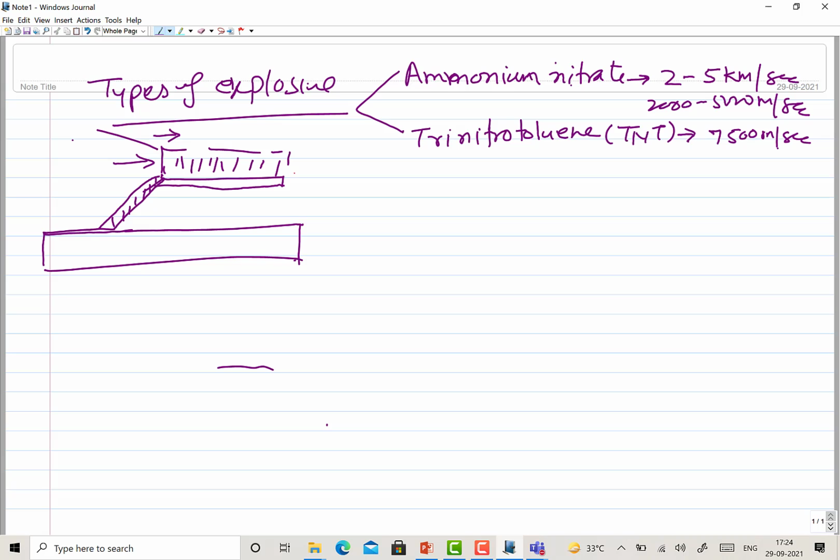So it will give you low collision angles. Something which bends fast, soft and ductile, of low yield strength, under the impulse pressure of the explosive will bend fast, leading to higher collision angles.